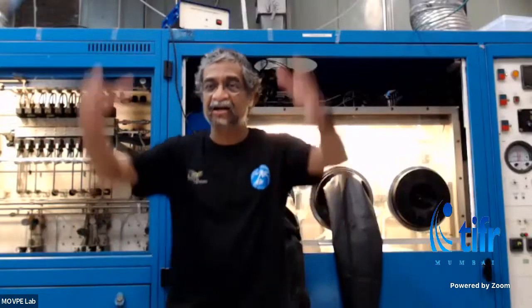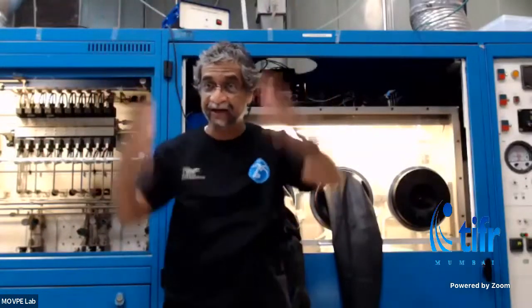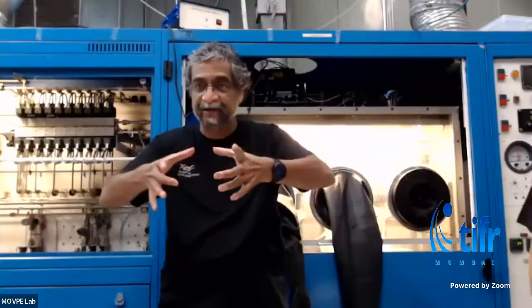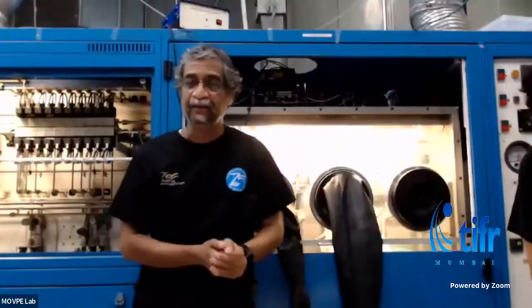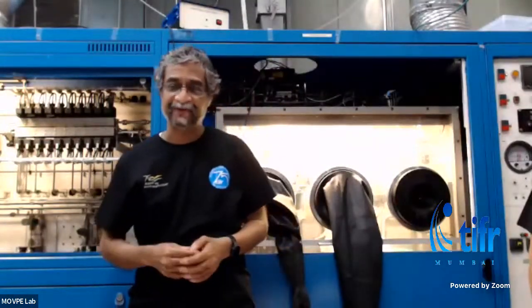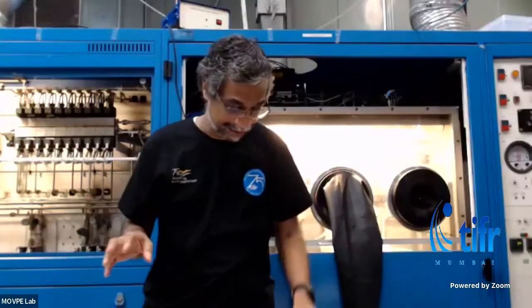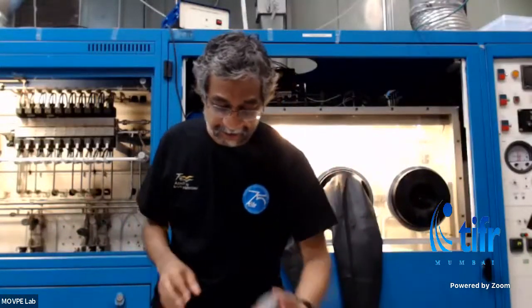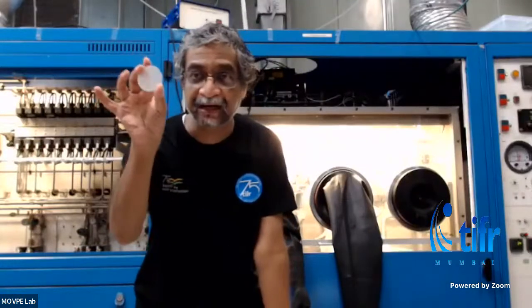You can grow large cylinders of sapphire, and then you can cut them and make crystals. You can get even big discs of sapphire. We use 2-inch. Our system takes 3 2-inch wafers. And sapphire is used because it's probably the cheapest material that you can grow on. This 2-inch disc of sapphire costs maybe $10 US if you buy it in bulk.